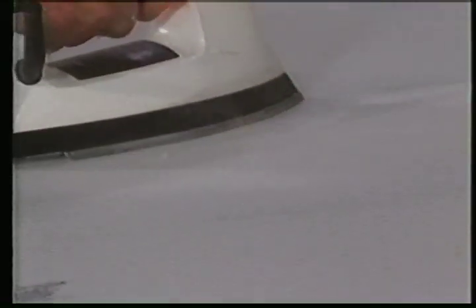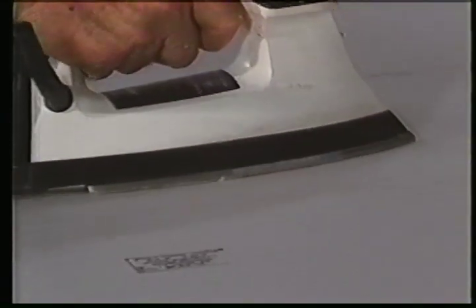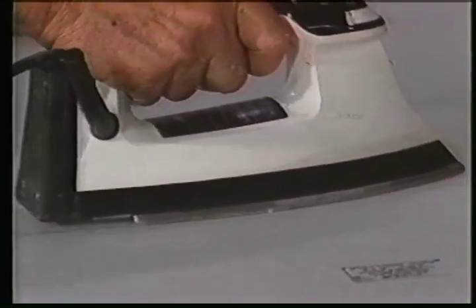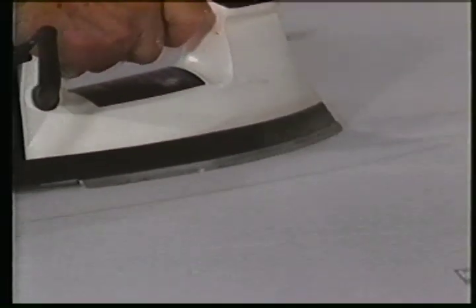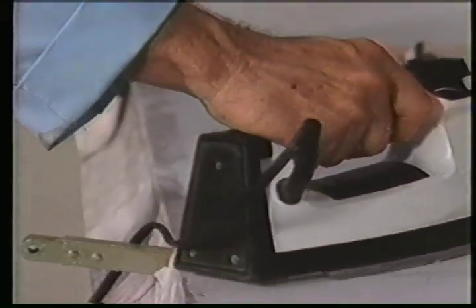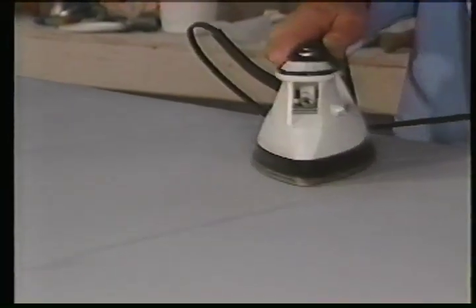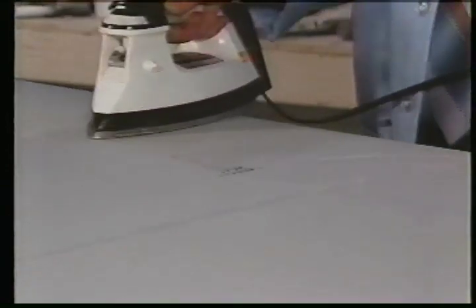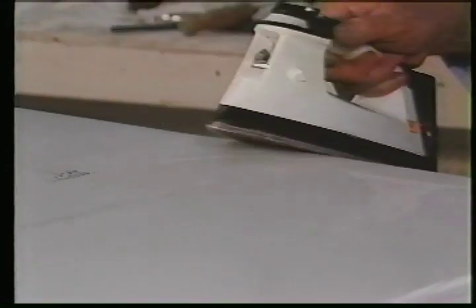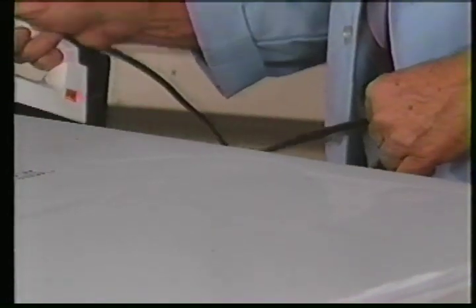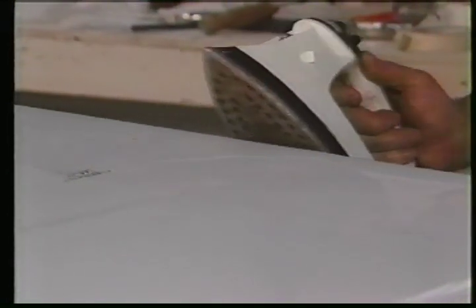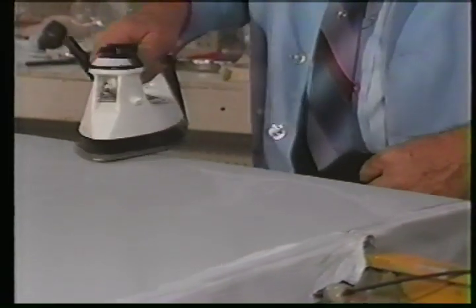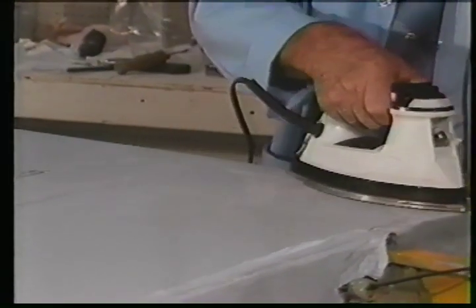The appearance of smoke from the fabric at the 350-degree iron setting indicates moisture on the filament surface being removed as steam and is normal and not cause for alarm. Fabric-forming structures such as a leading edge act as a heat sink and will require the lower end of the speed rate. The iron is first moved briefly from one area to the next rather than completing one area before moving on. After the first brief pass, the iron is moved carefully to contact all the fabric surface.